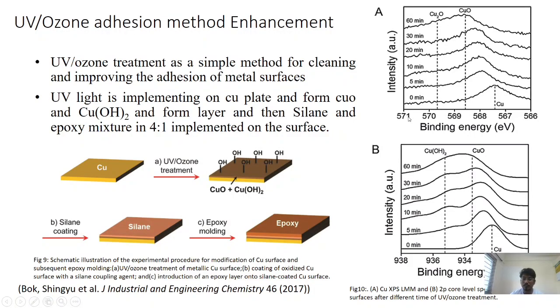Let's say at 0 minutes, when the ultraviolet light is not exposed to the surface of the copper, there is a binding energy of 567.4 electron volt. As we increase the time of the ultraviolet light on the surface of the copper, the binding energy peak is shifting to a higher value, which is 568.7 electron volt for the copper oxide. The same is the case for the copper hydroxide, which at 0 time is 932 electron volt. As we increase the ultraviolet exposure time to the surface of the copper substrate, the binding energy is shifted to a higher value, like 935.2 electron volt.